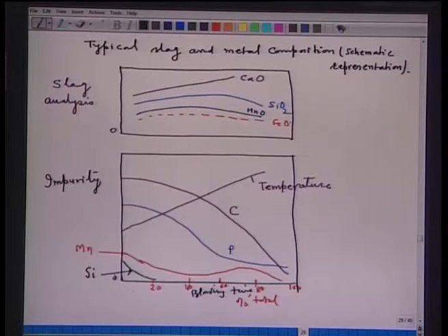Now, coming back to the removal of impurities and formation of slag. The x-axis shows the blowing time in percentage of the total, say 0%, 20, 40, 60, 80, 100%. The y-axis is the concentration of impurity. Concentration of carbon is higher than phosphorus, then manganese, and then silicon. As you blow oxygen, silicon oxidizes very fast. As you are seeing, silicon oxidation is mostly complete in less than 20% of the blow.